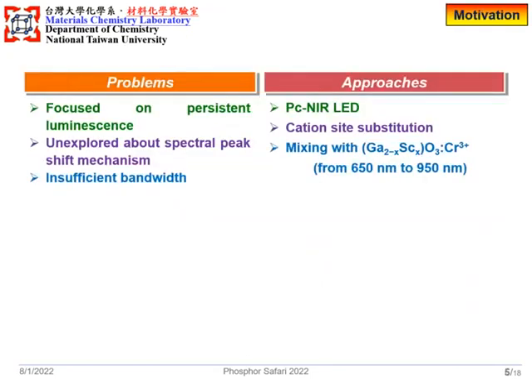From the previous research, we can realize that they focus on the persistent luminescence. The spectral peak shift mechanism is unexplored, and the emission bandwidth is insufficient. Hence, our approach is to make the pc-NIR LED package to evaluate the performance of our phosphor. The cation site substitution is applied to investigate the spectral peak shift mechanism. Finally, mixing with the phosphor of gallium oxide doping with scandium can extend our emission bandwidth.